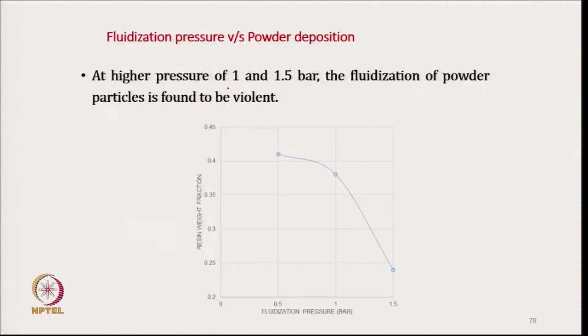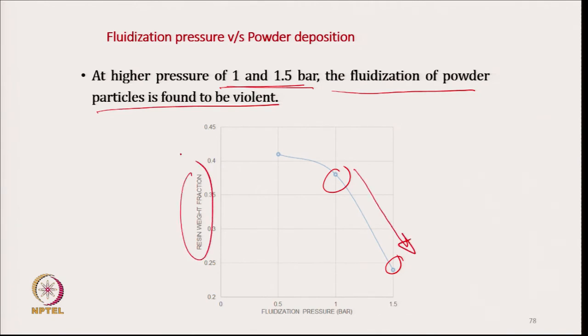At high pressure, 1 and 1.5 bar, the fluidization of powder particles is found to be violent. That violent nature is not actually required. Due to it, the powder behaves erratically and clogging may take place, which results in a reduction in the resin weight fraction. For proper deposition, we need proper cloud formation. The particles should not move violently; there should be smooth, light movement.